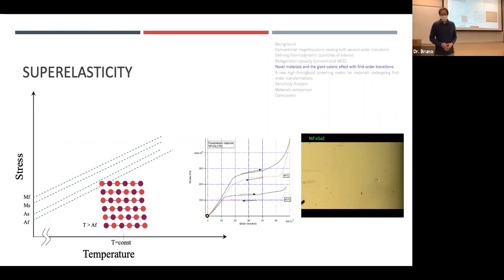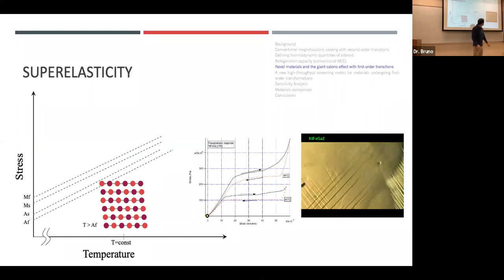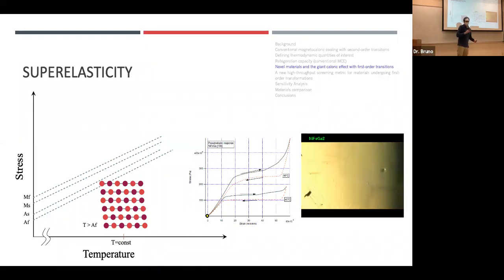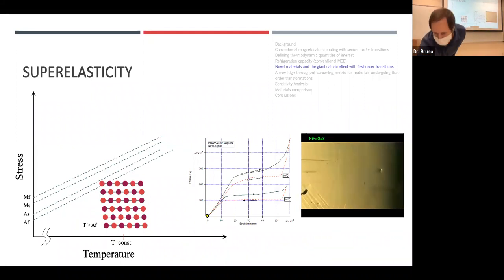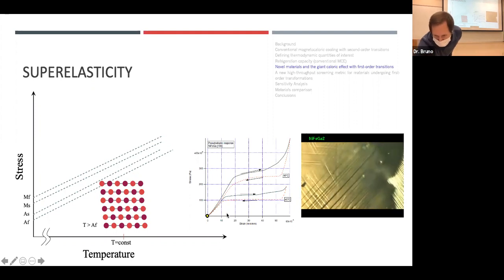So actually, when I was a graduate student, I polished up a single crystal of nickel iron gallium and looked at it under the microscope to see if I could observe the martensitic transition. I just used a set screw on the polished material, and I cranked down on the set screw until I could see something. And I did see some martensitic transition take place on the surface. Then when I released that stress by just unscrewing the set screw, it went back to austenite. Not completely, because there's some residual stress in there.